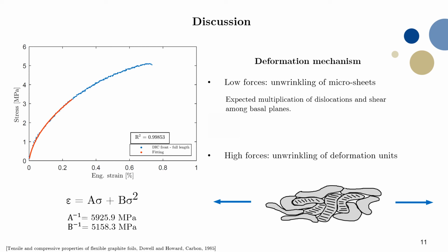So Dowell and Howard hypothesized a contribution to the deformation by both the unwrinkling of microsheets and unwrinkling of deformation units. The first contribution is more similar to the deformation mechanism of polycrystalline graphite and pyrolytic graphite, by means of dislocations and shear among basal planes. This can also be confirmed by a simple fitting. Here in the plot on the left, one can observe that the fitting has been taken with a power law, which is typical of polycrystalline graphite, and it's very good up to 3 megapascals. And here probably the contribution to deformation is given by the unwrinkling of microsheets.